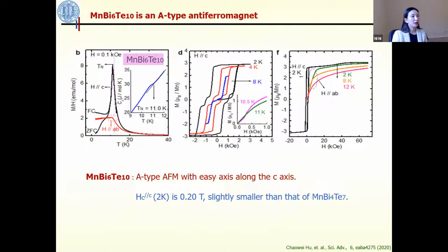Okay, so now I'll show you the magnetic property measurement of the 1610. You can see it also shows antiferromagnetic behavior here. It has a first order spin flip transition with the saturation around 0.2 Tesla. And the easy axis is still the c axis.